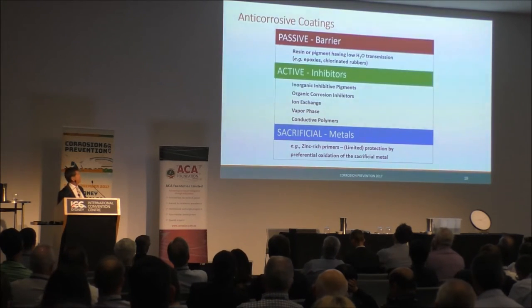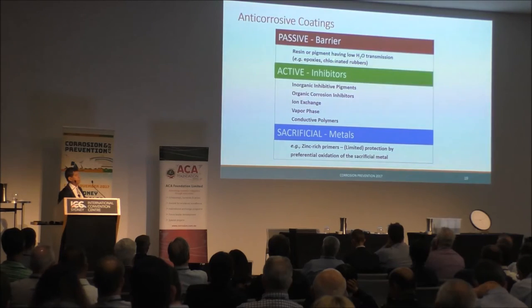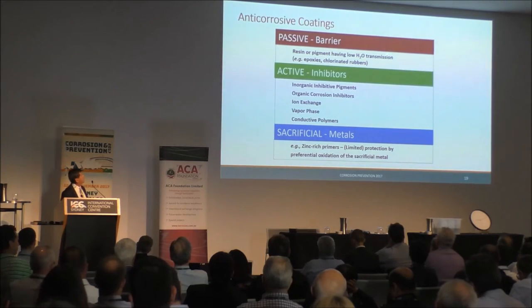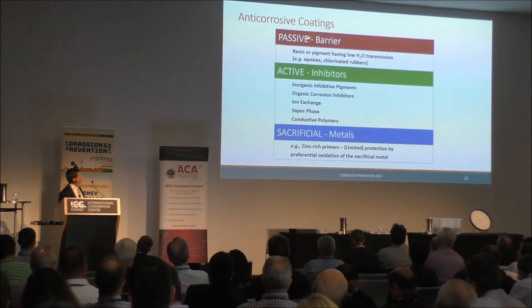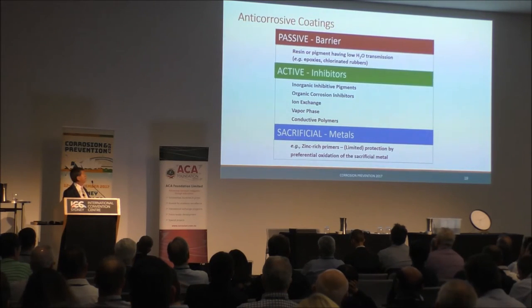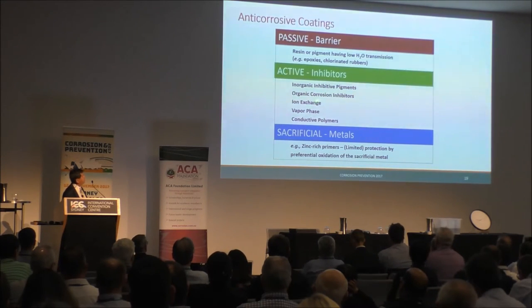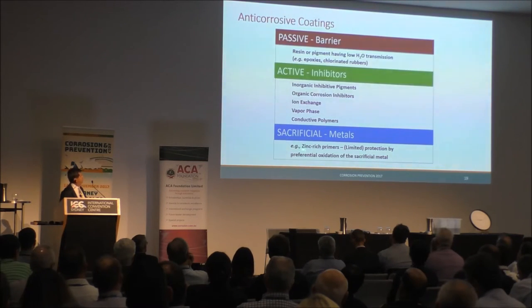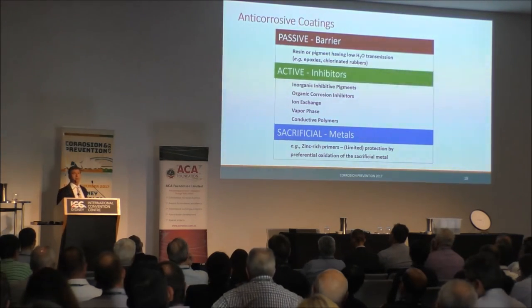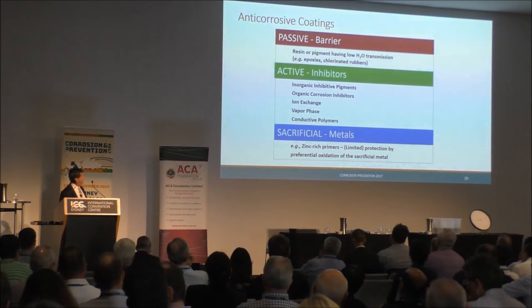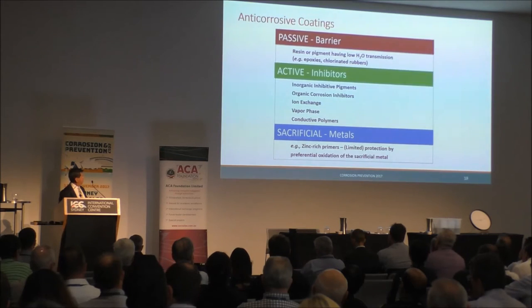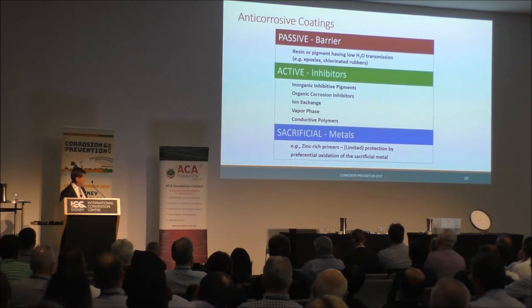So in simplistic terms, we usually just define the coatings as an option of either passive barrier coatings, as I mentioned, where the resin and pigment may have relatively low water transmission characteristics. So the paint can be thought of essentially as a barrier. Or active coatings with these inorganic type pigments, but it could be organic, and other types of pigments are used to influence the overall effect at the anodic and cathodic sites. The third general category is sacrificial methods, and zinc-rich primers would represent the most obvious example of very successful technology for providing sacrificial protection to steel systems and substrates.